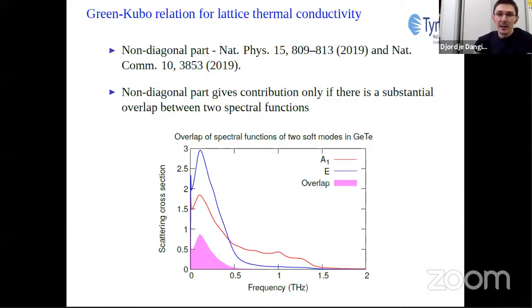The non-diagonal part has been already described in these two recent publications as the primary transport mechanism in amorphous materials. In the previous formula, it has a slightly different expression, and we can note that the non-diagonal part gives contribution only if there is a substantial overlap between two spectral functions of phonons with the same Q vector but different branches.